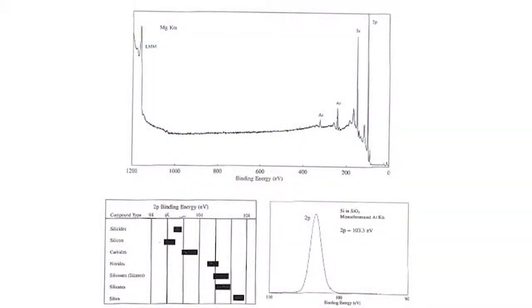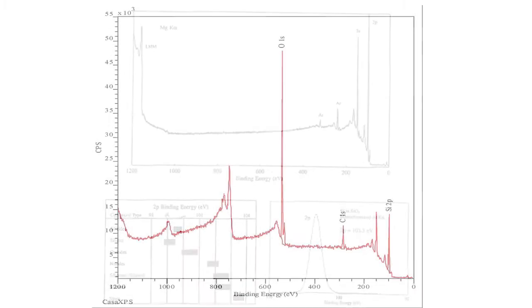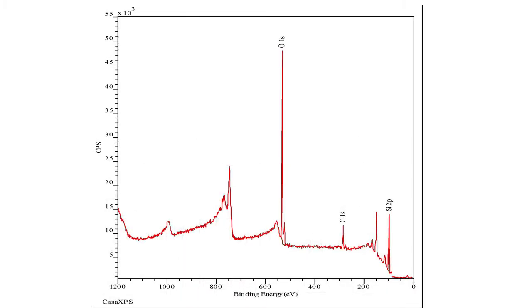This image shows a reference spectrum for silicon obtained with the magnesium K-alpha X-ray source. Each element has a unique XPS spectrum. The silicon 2P peak has different binding energies for different chemical states. This next image shows a spectrum obtained with a magnesium source on the surface of a piece of silicon. The native oxide on the silicon appears as silicon and oxygen peaks. The carbon is due to surface contamination.